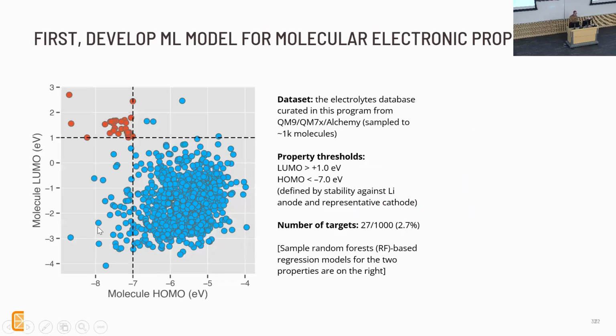And enter machine learning, right? So the first thing we did was develop a machine learning model for molecular electronic properties. We grabbed a data set from the internet that people have already built for a large number of molecules. The QM9 data set in particular is a good one. And we need to make predictions for things like the HOMO and the LUMO for these molecules. And we defined some property thresholds based on our application here, in this case specifically the stability against the lithium anode and some representative cathode. And we were able to narrow down in the training set the number of targets from a huge number to only 27. This is a sampling of the data set for the purposes of random forest training.